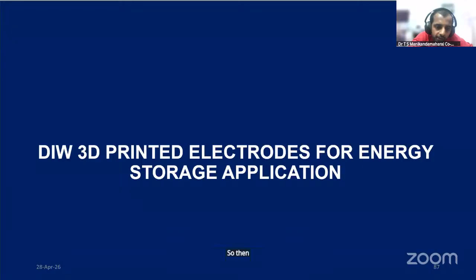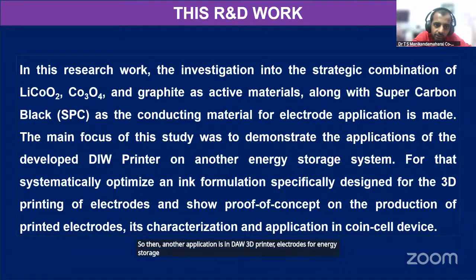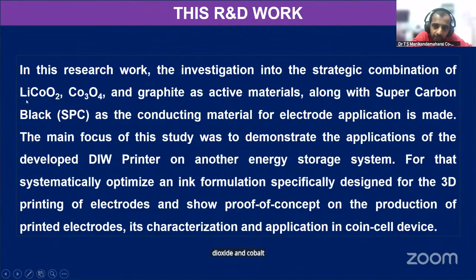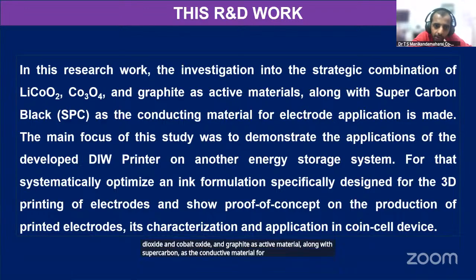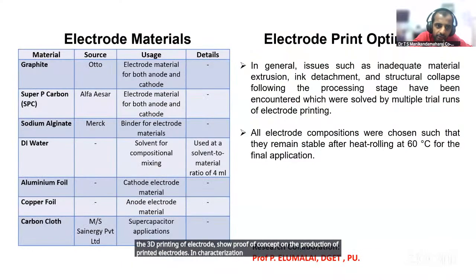Another application is DIW 3D printed electrodes for energy storage applications. In this research, an investigation into the strategic combination of lithium cobalt oxide, cobalt oxide and graphite as active material, along with super carbon as the conductive material for electrode application, is made. The main focus of the study was to demonstrate the application of the developed DIW printer on another energy storage system, with a systematically optimized ink formulation specifically designed for 3D printing of electrodes, showing proof of concept in the production of printed electrodes, characterization and coin cell device application.